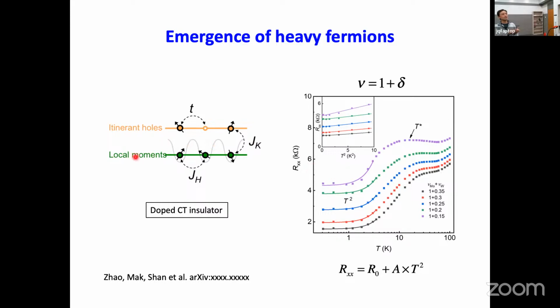Okay, so this is 1 plus delta. We keep a layer of local moment in the MoTe layer, and this is the resistivity versus temperature data at different filling factors. But the filling factor is such that we only change the filling of the itinerant carrier. The local moment is always kept at a triangular lattice of local moment. There's no change in the filling of the MoTe layer. Okay, so you can see a characteristic Kondo temperature, below which the resistance drops significantly, and you also develop this coherent transport of a T-square dependent resistivity at low temperature, which you can fit by this formula here with the T-square dependence.